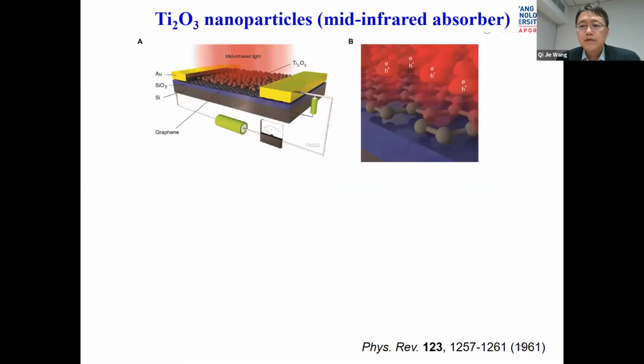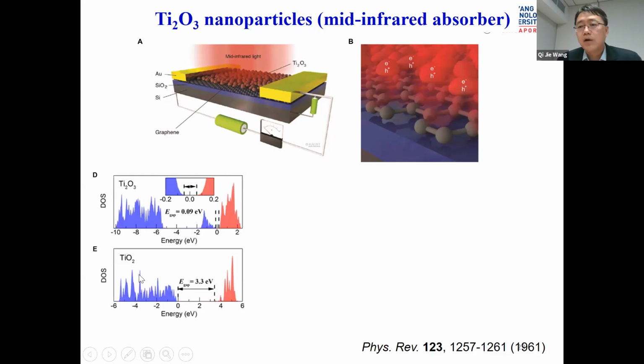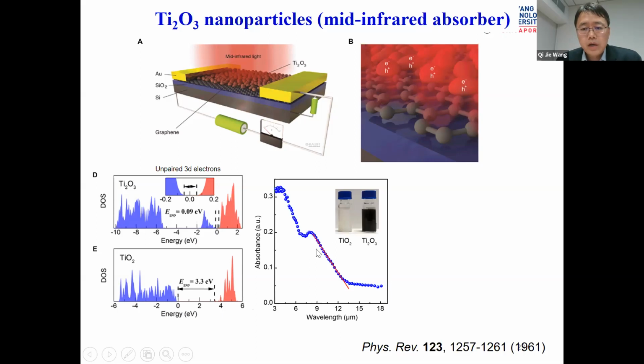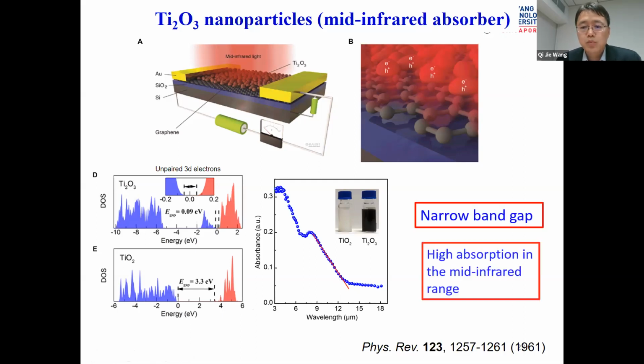And what we discovered is that this titanium(III) oxide, Ti2O3, nanoparticle, in fact, is a very interesting mid-infrared material. This material was actually already investigated in the 1960s, but its optical properties were not well studied. And we found out that different from titanium dioxide, which is a large bandgap material, in this Ti2O3, because of the dangling of the bond in this 3D electron states, an upper valence band can be created in the bandgap. So therefore, you can create a small bandgap in this Ti2O3, roughly about 0.1 eV. So therefore, this Ti2O3 is black in the visible region, because the light is absorbed. And through the absorption measurement, we can see the cutoff wavelength is indeed around 12 micrometers. So that's exactly what we need.